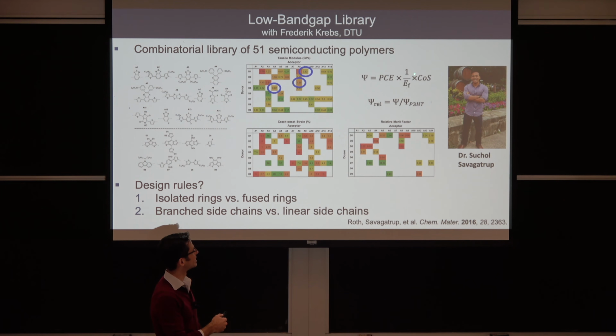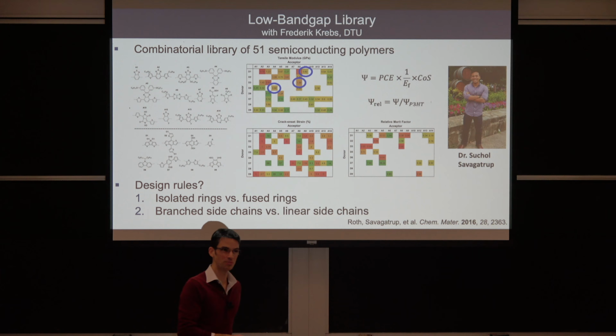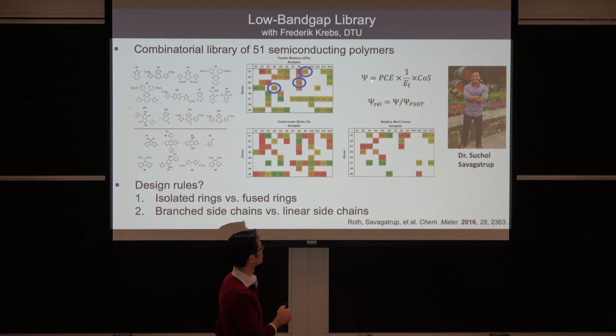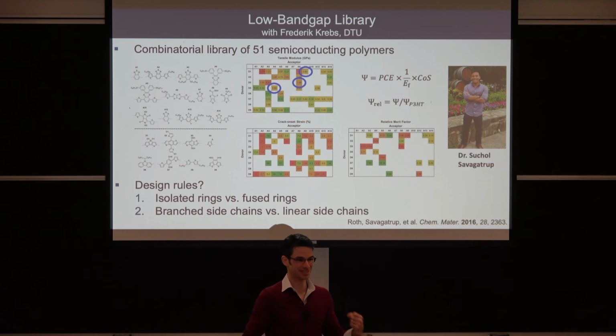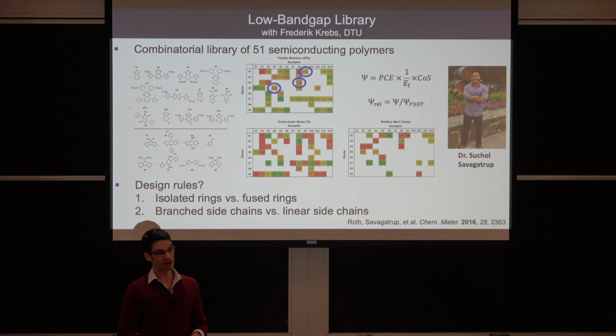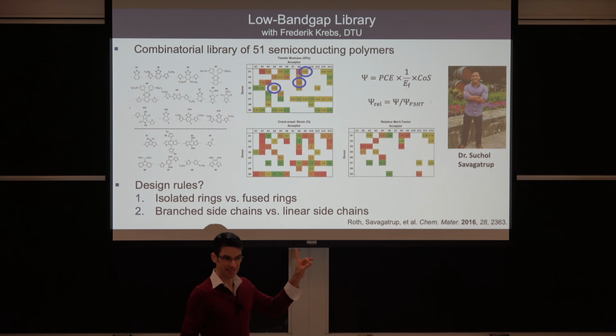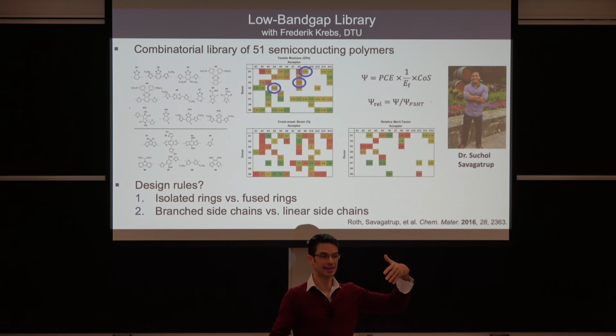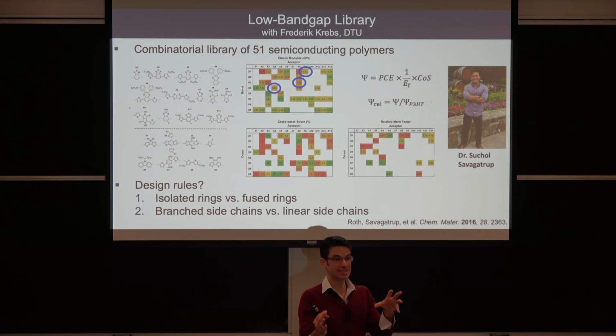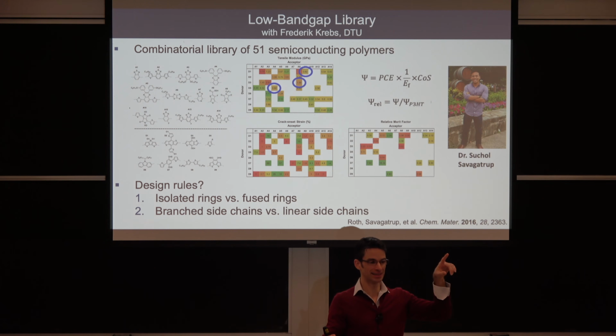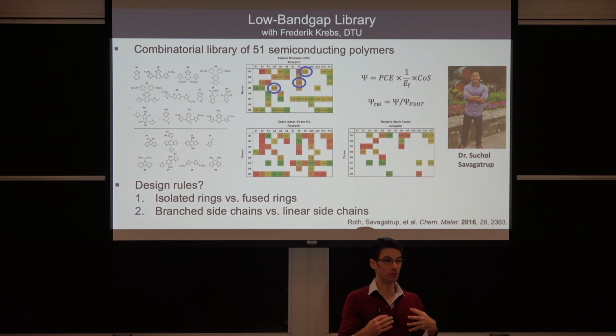We know that if you have a really stiff material, it tends to debond from other layers in the device stack. It tends to correlate with poor survivability, so we use the inverse. And we gave them all coefficients of 1 to 1 to 1, completely arbitrarily. But you've got to start somewhere. For the merit factor, for the UV-Vis experiment, we were interested in collapsing those UV-Vis parameters down to something that you could plot that would give you a big difference when you're comparing very, very similar spectra.